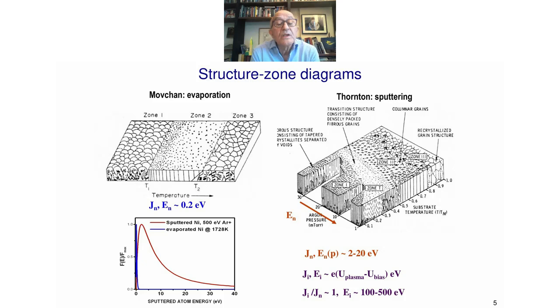Evaporated films have thermal energy of the condensing species. This is given in blue, like 0.2 eV in the graph. It is very low compared to the red curve, which is for sputter deposited species, or the species sputtered from the target, with a peak of about several eV extended to tens of eV. So Thornton in the 70s proposed the Thornton diagram for sputtering.